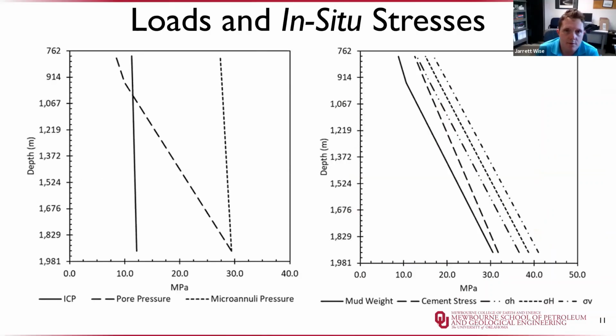So the following figures are the loads and stresses within the model from the simulation depth to the top of the cement depth. The internal casing pressure and microannuli pressure are determined from the static single-phase gas equation. The pore pressure, drilling fluid weight, cement stress, and minimum horizontal stress are all determined from the well drilling reports. And then the overburden stress is calculated from the Gulf of Mexico correlation. And the maximum horizontal stress is just the average of the overburden and the minimum horizontal stress.